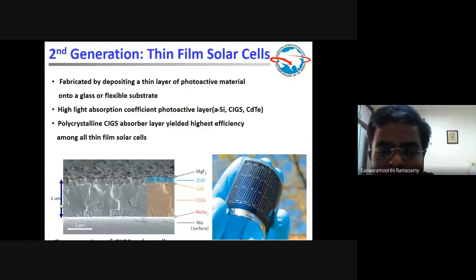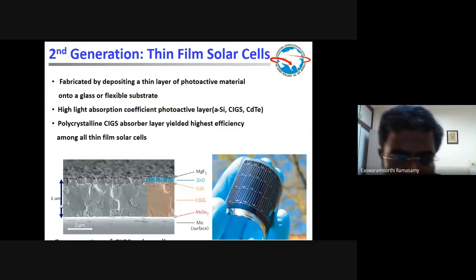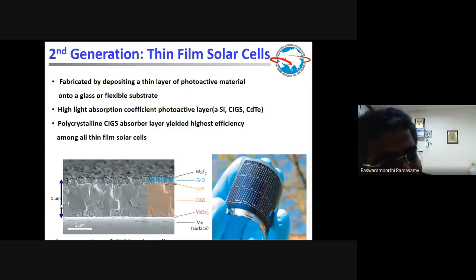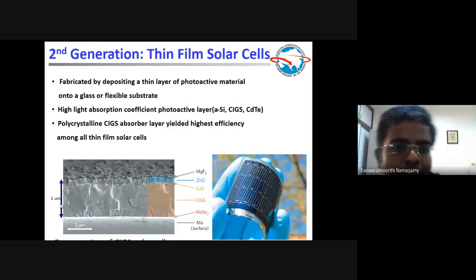The reason is nothing else. It's the physics behind this material's structure. CIGS is a direct bandgap material, so it can easily absorb the incoming photons. But in the case of silicon, it is an indirect bandgap. So the photon has to follow momentum conservation and all other related laws. So they need more depth to be absorbed by the material. That is the major difference.